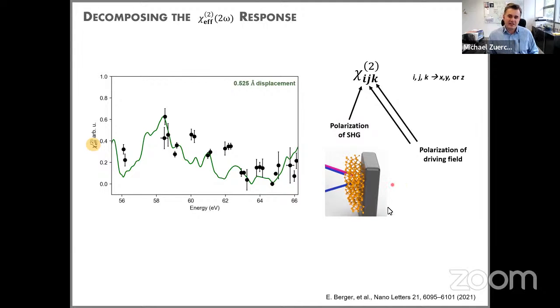Now, one thing we can do is, if we have our crystal clamped on our cryostat, we know, of course, what the orientation of the crystal is. We know what the crystal cut is. We know what the crystal planes are. We also know what the polarization of our FEL actually is. We know our FEL is p-polarized. So we know that both of the electric fields that cause the second harmonic are in plane, yeah? And the polarization of the SHG is what we don't really know in this case, but we can assume it's perpendicular or parallel, one of the two, but it doesn't matter for this kind of interpretation.